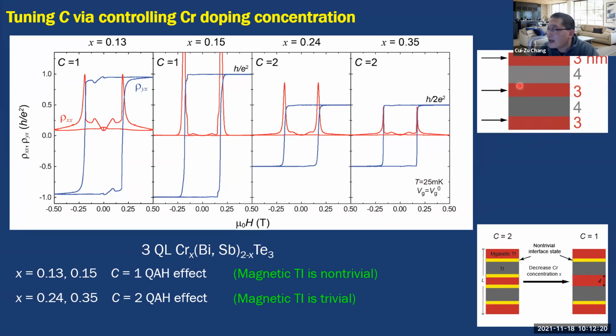We found that in this magnetic TI and this undoped TI, with the lower doping level, the Chern number is 1. With the higher doping level, the Chern number becomes 2. For the lower doping level, as I just showed you, the spin-orbit coupling is still strong enough to keep these magnetic TI layers in the non-trivial regime.